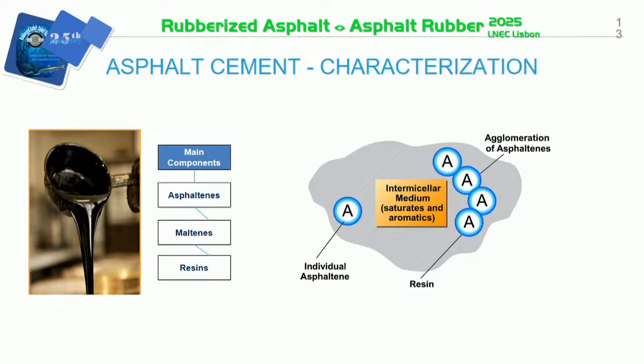The chemical balance of the base binder was monitored by measuring the proportion of saturates, asphaltenes, maltenes, and resins. This process is extremely important because crumb rubber tends to chemically unbalance the asphalt binder composition. Therefore, it is necessary to adjust the formulation of the asphalt cement using rejuvenation agents to restore the proper chemical equilibrium and ensure consistency in performance.